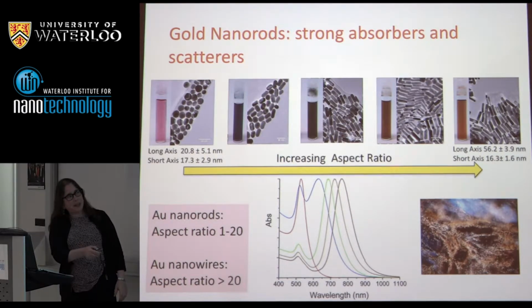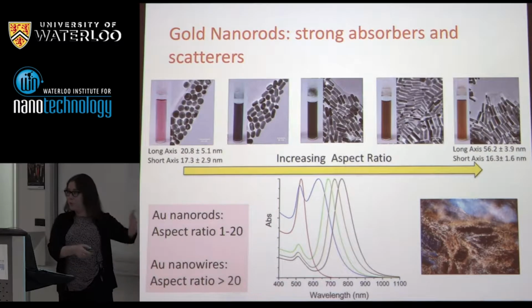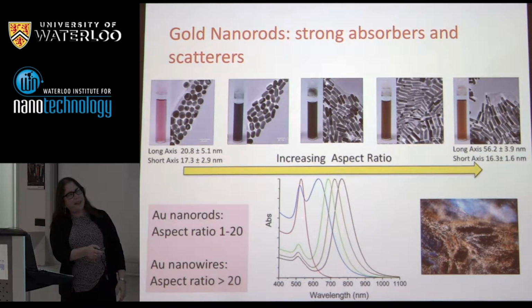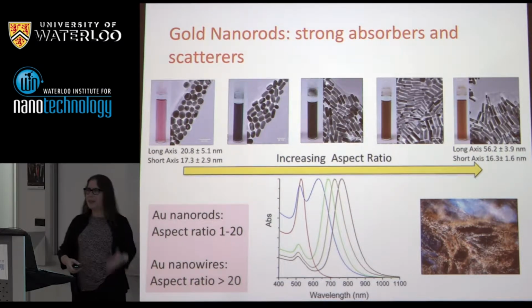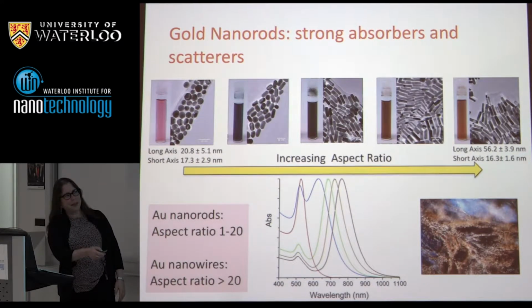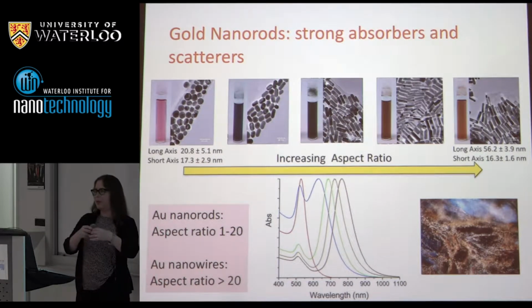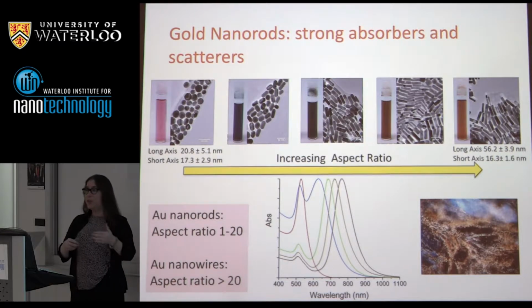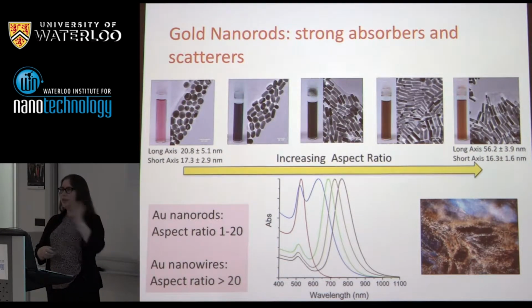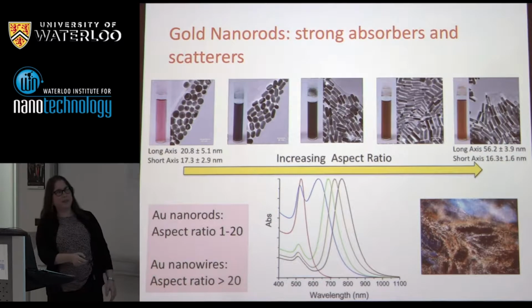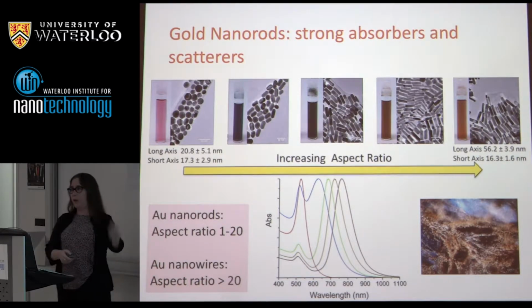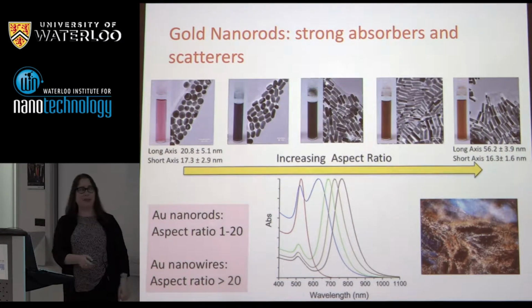And if you take spectra, here they are. So here's our 1 plasmon band we had before for a sphere, from Gustav Mie, from Michael Faraday, et cetera. And then as we collect spectra for these guys here, you see we have 2 bands now. And how people understand this, our 1 plasmon band is splitting into 2. So we're absorbing light and scattering light, it turns out, too, along the short axis and the long axis of these particles. And so as you make the particles have a higher aspect ratio, the longitudinal plasmon mode, the long axis mode, shifts to lower and lower energy or longer wavelength. So the shape of the particle dictates where the light's absorbed. So that's going to be an important feature that we'll see.